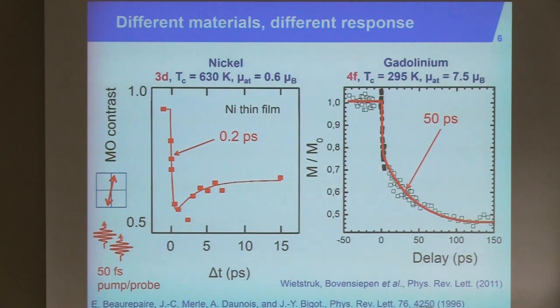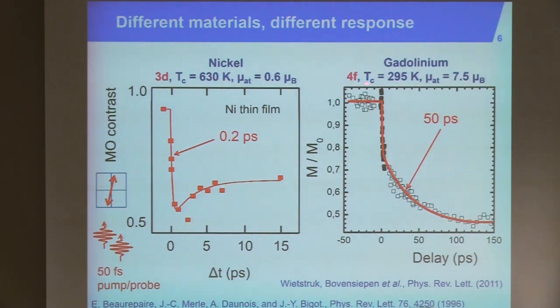You can do this for different materials. Many groups have started to reproduce this effect. Two typical results show that while in many cases you see timescales of typically a few hundred femtoseconds, there are materials which show much slower demagnetization. For instance, the 4f material gadolinium shows that it takes typically 50 picoseconds to reduce the magnetic moment, with a two-step process: a rapid process in the first one or two picoseconds, then a slower process. It's not so strange that it has different behavior — this is a 3d ferromagnet while gadolinium is 4f, with a lower Curie temperature of 295 Kelvin, a very high magnetic moment. The take-home message is simply that gadolinium is much slower than cobalt, nickel, and iron — keep that in mind.